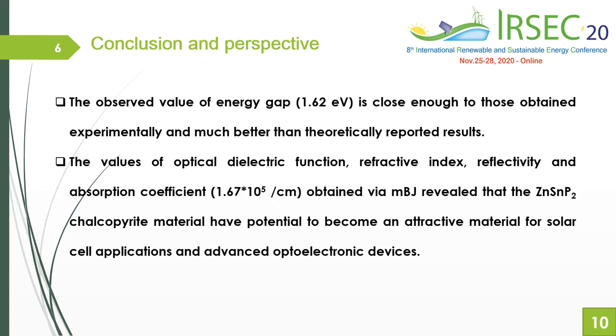In summary, the observed value of the energy gap is close enough to that obtained experimentally and much better than theoretically reported results. The values of the optical dielectric function, refractive index, reflectivity, and absorption coefficient obtained within mBJ reveal that the ZnSnP2 chalcopyrite material has the potential to become an attractive material for solar cell applications and advanced optoelectronic devices.